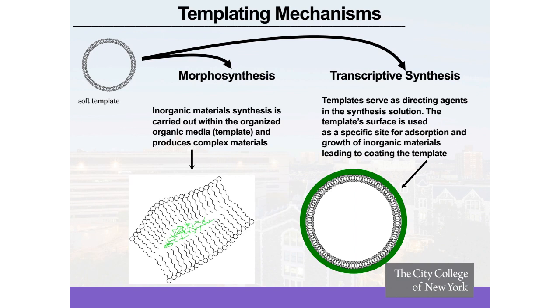Another area of interest in my research lab deals with the templating synthesis of materials and looking at different templating mechanisms. Specifically, we're interested in being able to use soft templates, such as liposomes or vesicles, where we can introduce these organic self-assembled structures to inorganic materials and synthesize using these organic layers as a template. Such a particular example allows us to use a transcriptive synthesis where the vesicular or liposomal structure is used as a template to grow on the outside of that surface a very thin layer of a metal oxide, such as silica, and so we can generate hollow spheres.